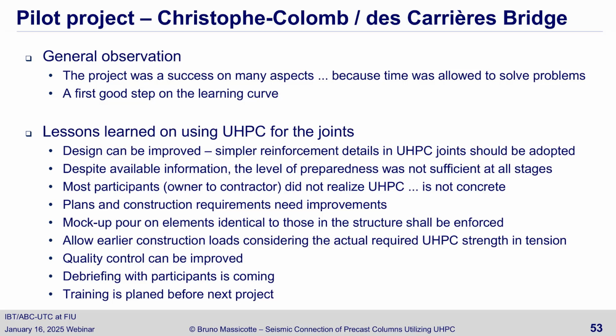other than the compression test? Yeah, well, like Bruno said, that is what we're going to do in the future. What we did in the field is we tested for workability. Also, we tested for the mass of fiber that we put in the mix, because it was with an on-site truck. So we tested the amount to make sure that we had the prescribed amount of fiber. And afterwards, we took some concrete specimens to test for compressive strength. But as the project went along, we also took specimens for anchorage and some bending.